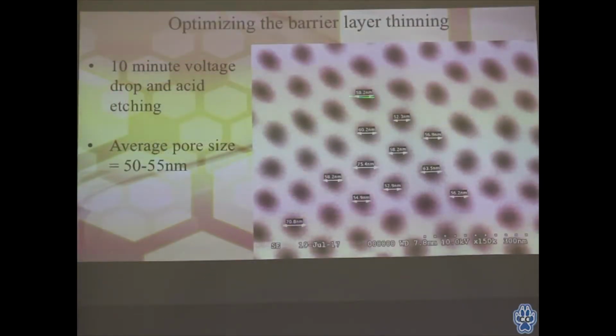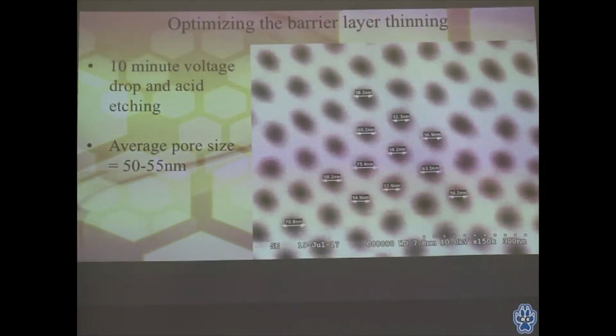So I'm just going to go into optimizing the barrier layer thinning. At first we did a 10-minute voltage drop and then an acid etching for 10 minutes using 0.1 molar phosphoric acid, and we took it to the SEM and we found that we did increase the pore size on average without removing the entire oxide layer and removing all the pores. Average pore size was around 50 to 55 nanometers.